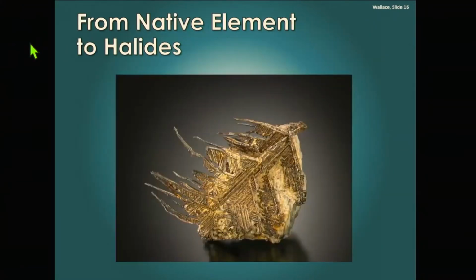So let's start out with the native elements. Typical native elements that we see in terms of silver, something like, of all the silver that's mined, 2% is native silver. So it's a pretty small percentage. When we see silver, it's almost always in wires. But there are two other times we don't see it in wires. One of them is a spinel twin. This is a nice spinel twin. It's about 5 inches across. This is from a relatively recent deposit in